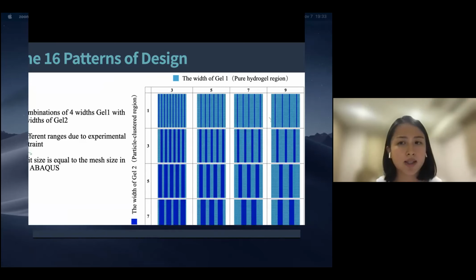So here we designed the 16 patterns of hydrogel film. We select 0.3 millimeter as our unit size, and the range of gel 1 will be from 3 to 9, increasing by 2 as the interval. And the range of gel 2 was from 1 to 7, and it also increased by 2 as an interval as well. So why we select 0.3 millimeter as a unit size